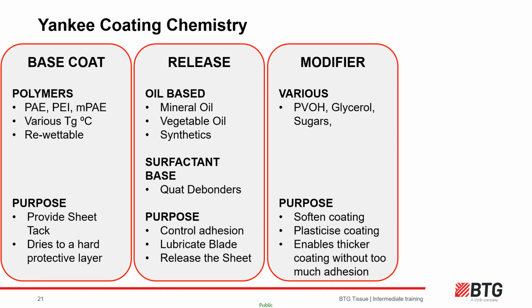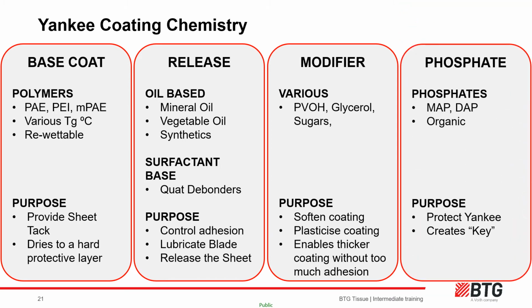Rheology modifiers soften or plasticize the coating, altering its film flexibility, often retaining moisture. Using them can enable us to develop a thicker but soft coating layer without making the coating go too hard, which is thought to encourage bulk and bulk softness and improve doctorability and coating refreshment. Phosphates are added for Yankee protection to provide a key on which the base coat can more easily adhere, thus increasing coating to Yankee bond efficiency.